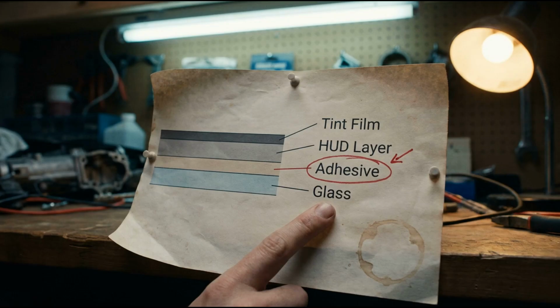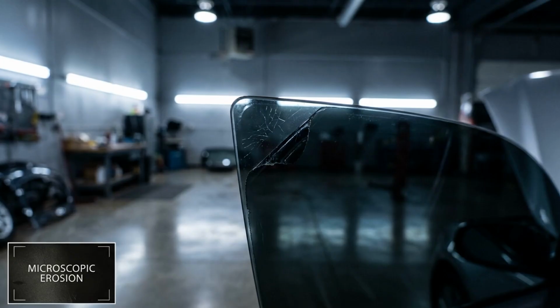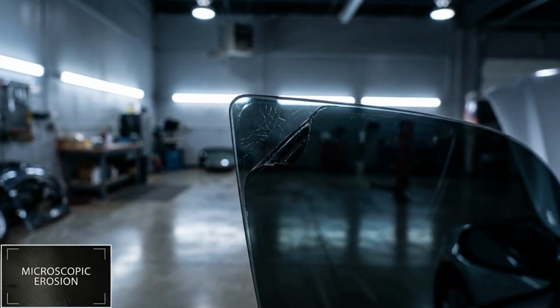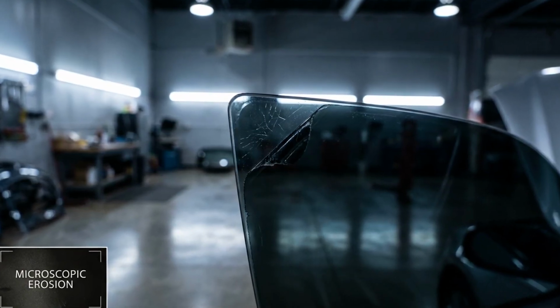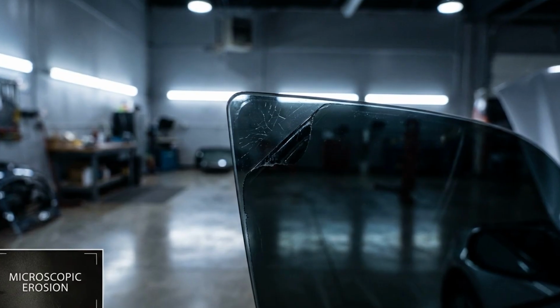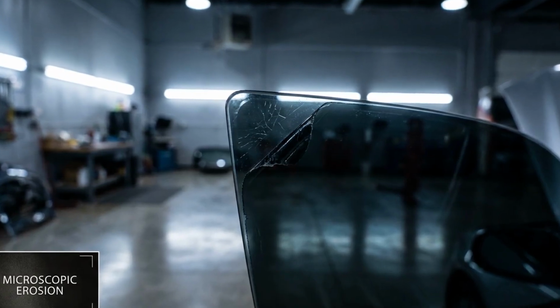On tinted rear windows, side windows with aftermarket tint, or a windshield with a heads-up display film, vinegar is a problem. Acetic acid can migrate through the edge of the tint film over repeated exposure and etch or lift the film adhesive underneath. Damage is invisible for months and then shows up as bubbling or edge lifting.